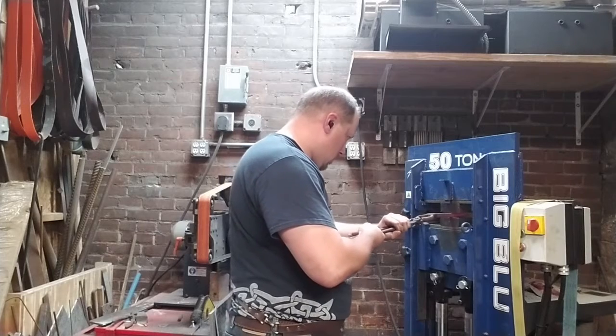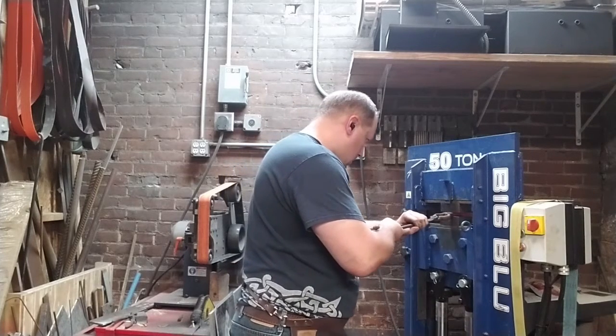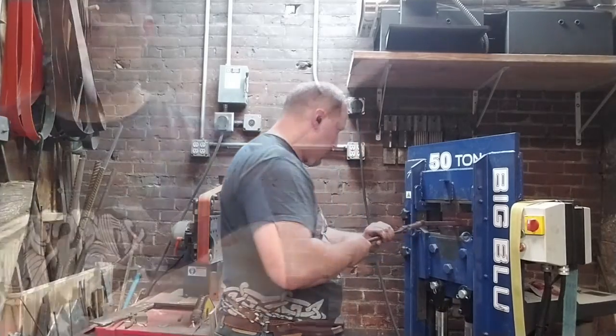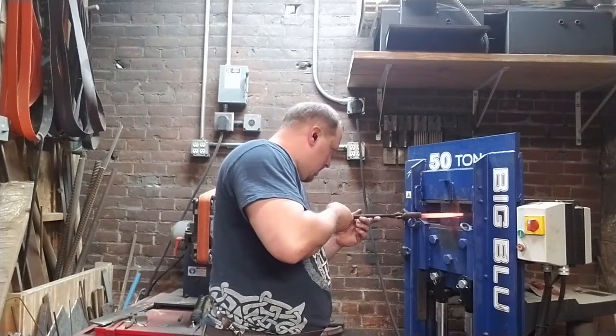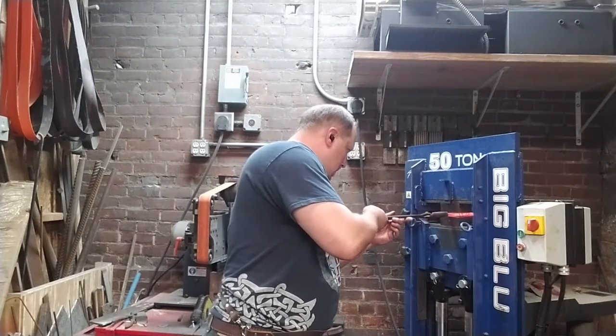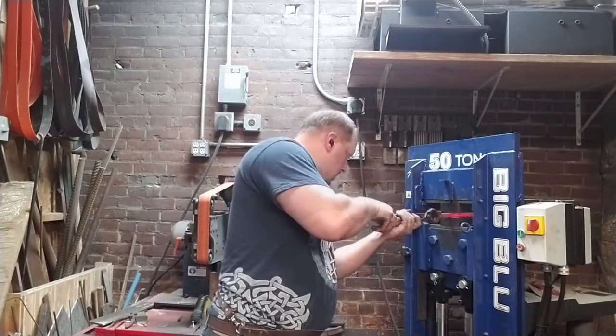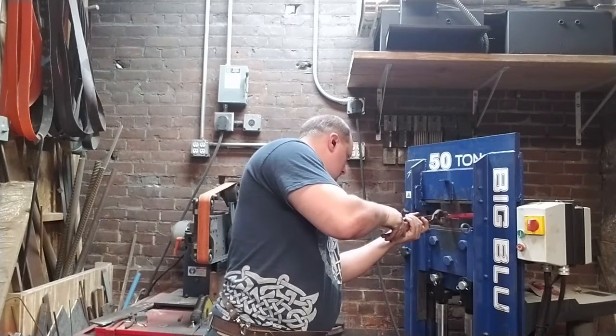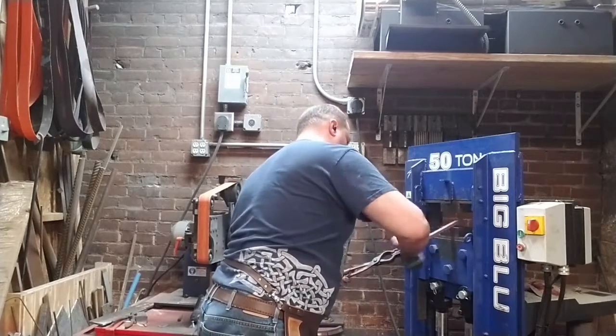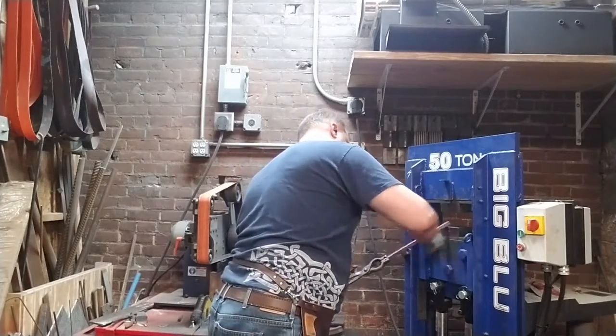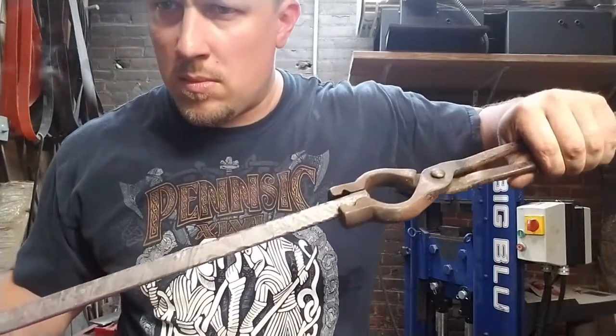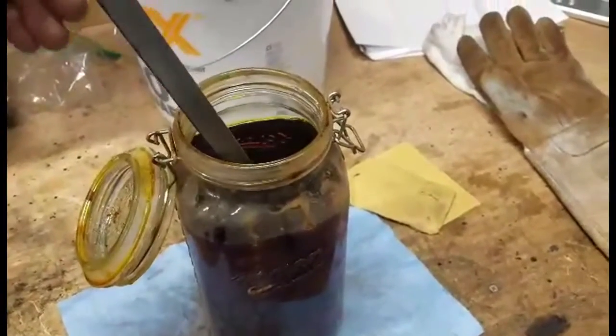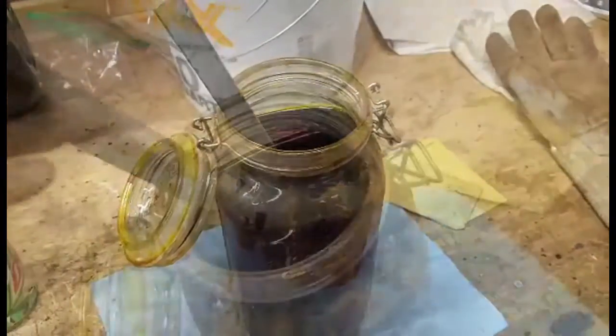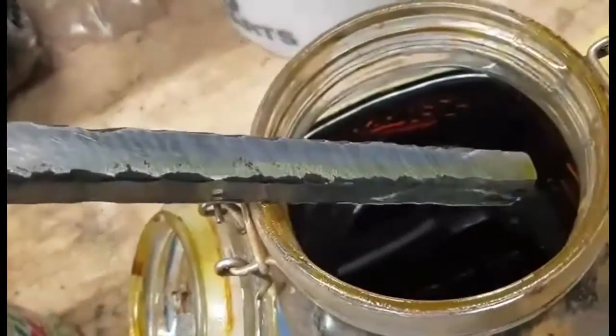Now we're going to forge that back down, because we do need square bars so that they can weld up on top of each other, and that's what we're doing right here. I think it came out very nice. I think here what I decided to do was make my squares actually a little bit rectangular, so that when I went to do the final forge weld I had a little more surface area, and when I drew out the profile of the knife I would have more room before I started distorting the twist.